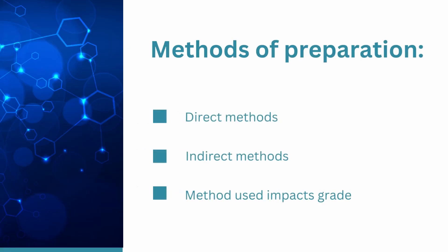So let's review this now. Magnesium stearate is a material that is chemically synthesized from a suitable magnesium compound and fatty acid. There are several synthetic approaches in use, all of which can be broadly divided into two groups: Number 1, the so-called direct methods, which involve reacting aqueous solutions of magnesium chloride with fatty acids or sodium stearate; and Number 2, indirect methods, which involve the production of a sodium soap by reacting fatty acids with sodium hydroxide, followed by the addition of magnesium oxide, hydroxide, or carbonate, which then precipitates out the magnesium stearate. It is important to note that the manufacturing process has an impact on the grade of magnesium stearate produced, but we shall touch on this later in the video.